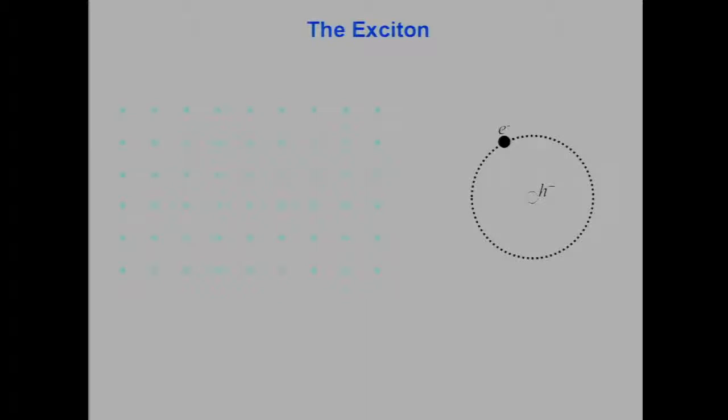Again, you miss all the details here on the slide, but basically the cyan points here represent lattice points on the crystal, and this exciton resides over several unit cells within the semiconductor. There is a typical radius that is called the Bohr radius that tells you how far apart the electron is from the hole. And if we now take this exciton and put them not in large bulk semiconductor, but in very small particles called quantum dots, nanoparticles, then the fact that the size of the particle is similar to the size of the exciton brings about quantum confinement effects.